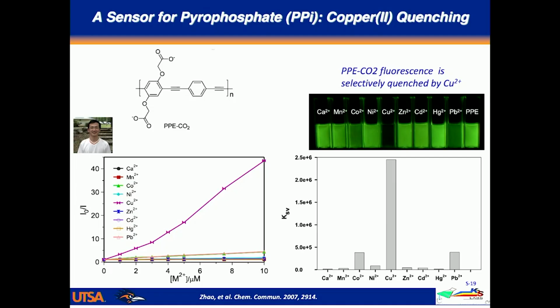And what I'm showing here is basically a summary of the result. This is the fluorescence of a series of vials of the polymer, and it's green fluorescent. And what you can see is when you add 10 micromolar of all these different metal ions, most of the vials are still fluorescent, but the one that has copper-2 is dark. And so that means that copper-2 is the most effective at turning off the fluorescence of this polyelectrolyte.